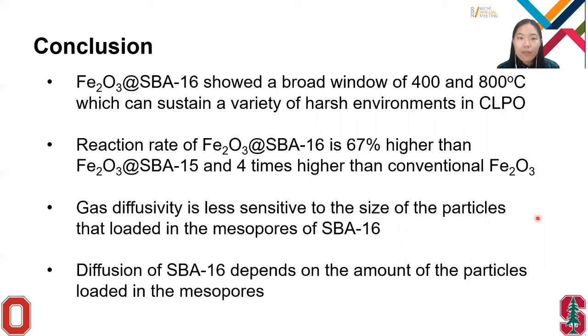And we found that the conversion rate of SBA-16 supported iron oxide nanoparticles is 67% higher than SBA-15 supported nanoparticles, and it is 4 times higher than the conventional Fe2O3 sample. And from dynamic Monte Carlo simulations, we found that the diffusion in the SBA-16 sample is less sensitive to the particle size, and the diffusion in SBA-16 mainly depends on the amount of the particles that are loaded in the mesopores.